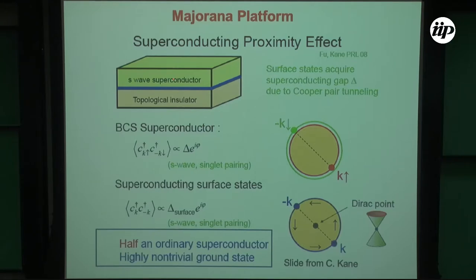On the topological insulator surface, you have a half Dirac gas, as I showed yesterday. You have half the degrees of freedom missing. So you have spin helical locking, spin-momentum locking. Now when you introduce Cooper pairing, you're dealing with superconductivity in a half Dirac gas. This is different from superconductivity in a conventional 2D electron system. So now we have half the degrees of freedom missing. Then you can calculate that this superconductor is half of an ordinary superconductor, and whose vortex has a highly non-trivial ground state. That's the Fu-Kane result, that half of an ordinary superconductor will have